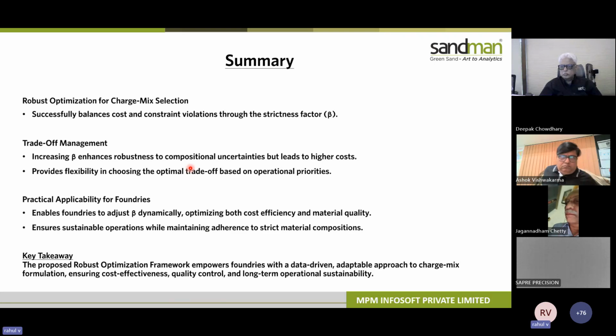So the summary of this section is as follows. The robust charge mix optimization helps in successfully balancing between cost and constraint violation through the strictness factor beta. So with an increase in beta, basically the strictness factor, which has to be increased during uncertainties, will give you a higher cost, but still you'll be getting your chemistry first time right. On the other hand, when there is no uncertainty, you can very well rely on the typical formulation, which will give you the least possible charge mix.